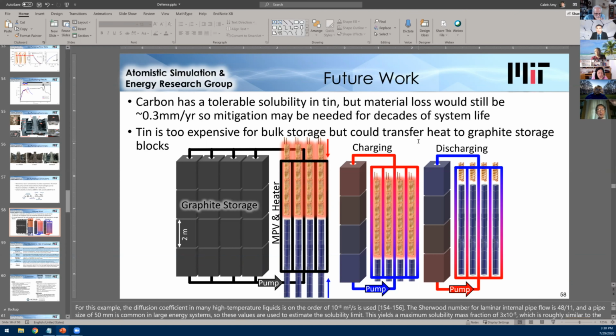We probably expected that from the beginning, but we designed all the mechanical systems to accommodate the only affordable material combination. And the mechanical systems finally worked. The pump rotated, it mechanically worked. It didn't melt or anything, but the material limitations prevent pretty much any liquid from being stored and transferred at this temperature. Well, that's pretty discouraging because that's more difficult to solve.